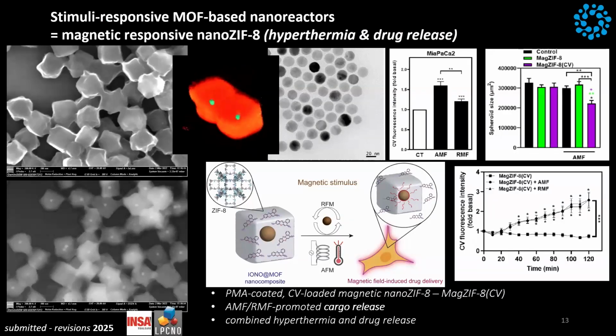In collaboration with the people in Toulouse, we have also done this with magnetic nanoparticles. Again, it's the same system. We make nanoparticles. It can be cubes, spheres, rods, tetrapods, whatever. As long as you put CTAB on top of it, you can grow ZIF-8. This is the same with different detectors. And you see that in all of these kinds of cubes, you have a magnetic core in the middle. Okay, this is what we wanted to do.